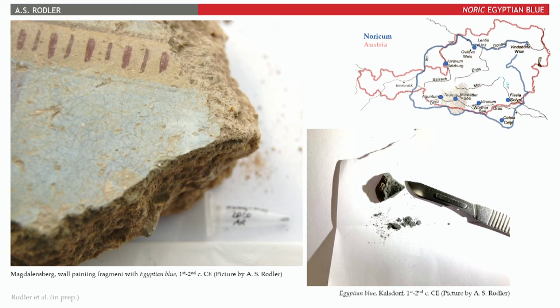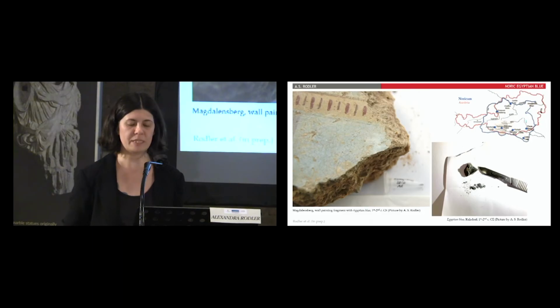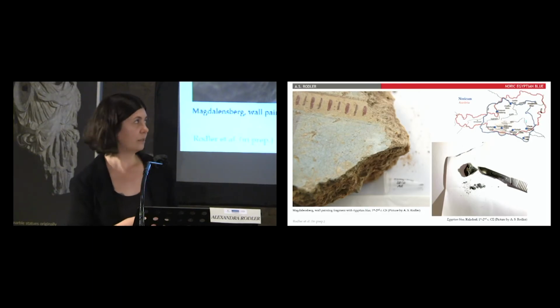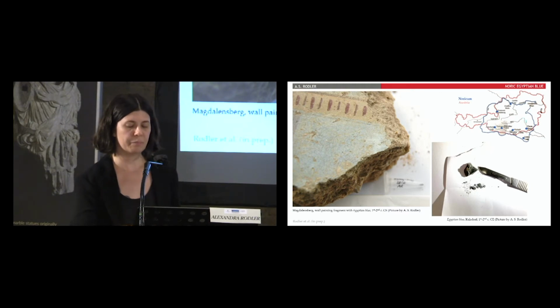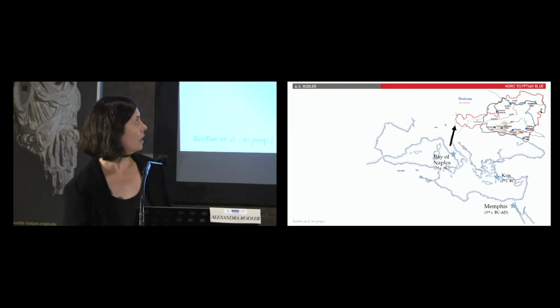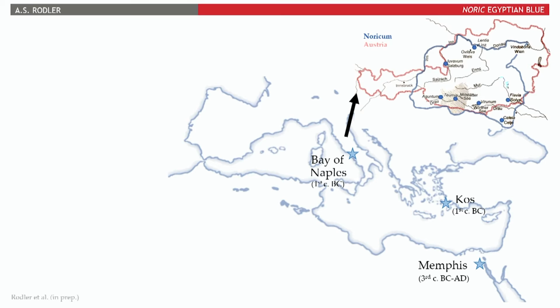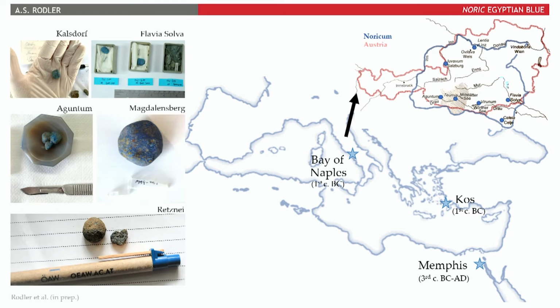workshops, we know that. So I mainly use samples from Roman wall painting fragments and compare between different Roman sites across Noricum. These are here with the blue points on the tiny map. And also compare to central Italy. And besides Egyptian blue from wall paintings, I'm also looking at Egyptian blue pellets that were found in Noricum. So for investigating trade and local production, I'm looking at the locally available resources such as calcium-rich sands and copper that might have been used for Egyptian blue production there.